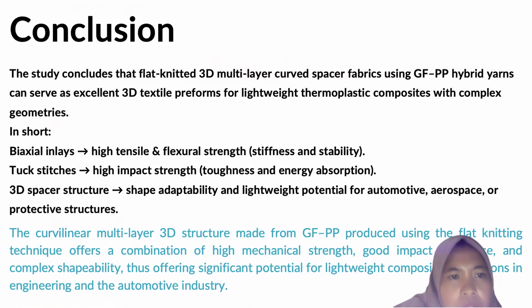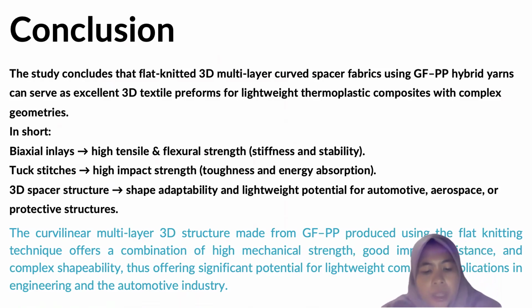Conclusion: the study concludes that flat knit three-dimensional multi-layer curved spacer fabric using glass fiber polypropylene hybrid yarn can serve as an excellent three-dimensional textile preform for lightweight thermoplastic composite with complex geometry. In short, biaxial inlay gives high tensile and flexural strength, stiffness and stability. Tuck stitch gives thickness, high impact strength, toughness and energy absorption. 3D spacer structure gives shape adaptability and lightweight potential for automotive, aerospace, or protective structures.